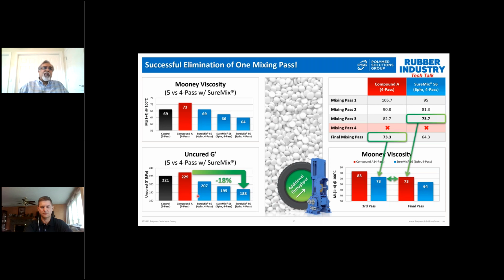Secondly, with the lower G prime, we know downstream processing is much improved. We won't have time to cover it in this, but what the customer did see, in addition to the lower viscosity, was an increase in stiffness or modulus of the tire lugs. And we have now figured out why. SureMix actually prevents reversion. So since this is a natural rubber formulation, the tire tread does not revert. We are able to maintain a higher modulus, which is beneficial.